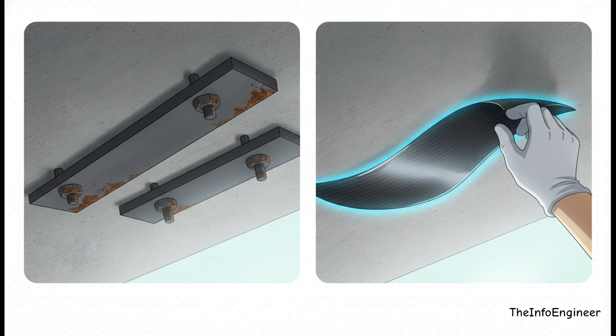Traditionally, if a slab lost its strength, we'd bolt these heavy, thick steel plates to the underside. But those plates are heavy, they're super hard to install overhead, and honestly worse, they are susceptible to the exact same corrosion that ruined the rebar in the first place. Today, though, it's a real game changer. We use CFRP, carbon fiber reinforced polymer systems like Tyfo. CFRP has a massive strength-to-weight ratio. It's chemically inert, meaning it will literally never rust, and it's only 2 to 5 millimeters thick, meaning you don't lose overhead clearance in places like basement parking garages.